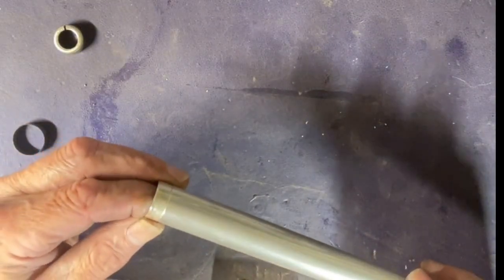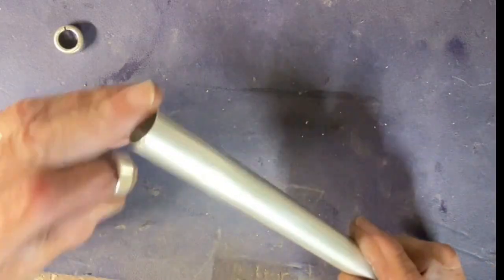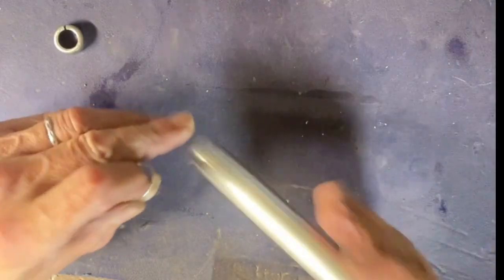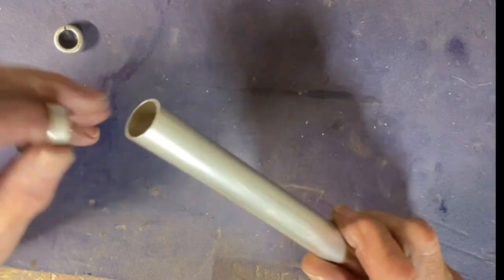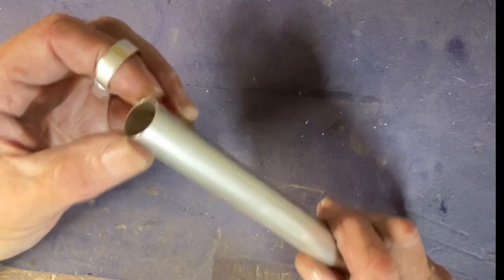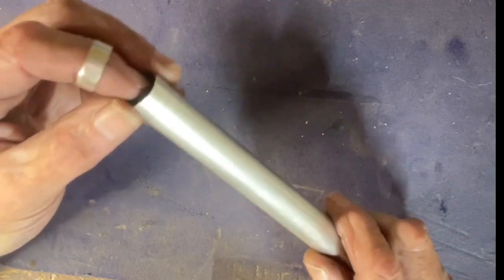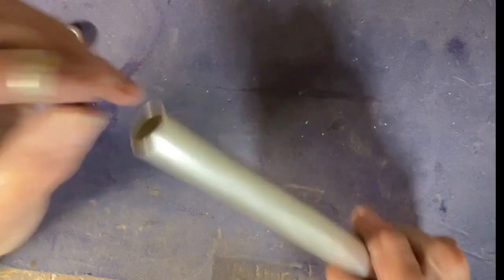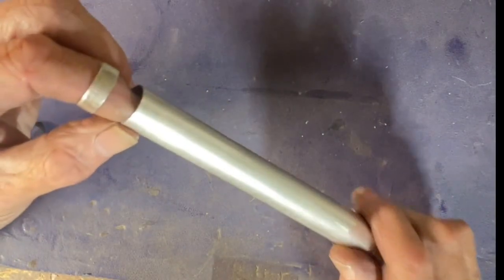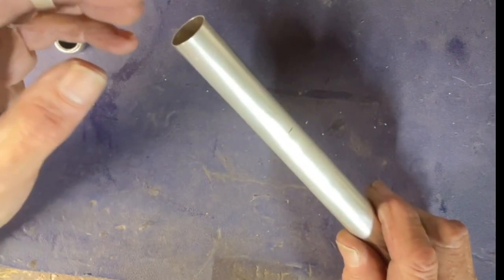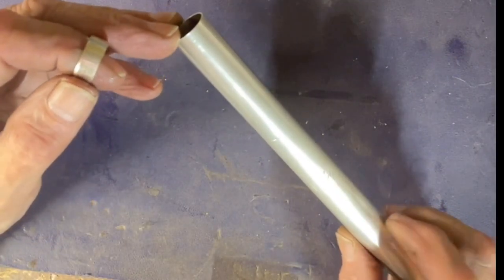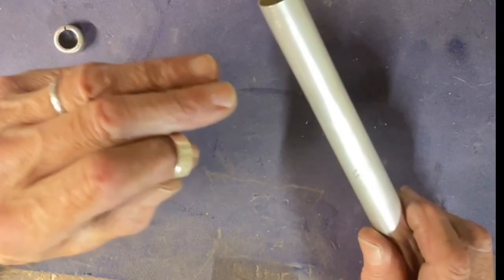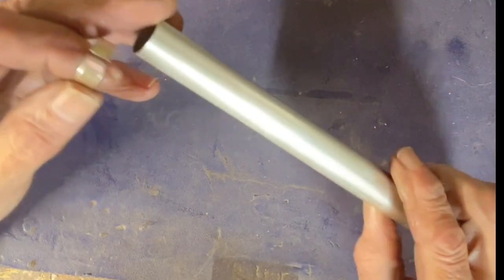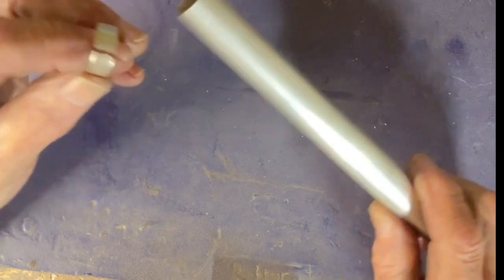So I've cut the top end off, and I've also cut the bottom end off. In this case, as I mentioned, this is a half-hard tubing, and now it's been hardened by physical reduction. So the part that got squeezed down has some memory, and it wants to return to its former size. Quench annealing, stress relieving, precipitation hardening, some of those things can alleviate this to an extent. It can change the temper of the head joint tubing, and it will have some effect on its response. For this head joint, I want it to be pretty spring hard, so I'm going to leave it as is.